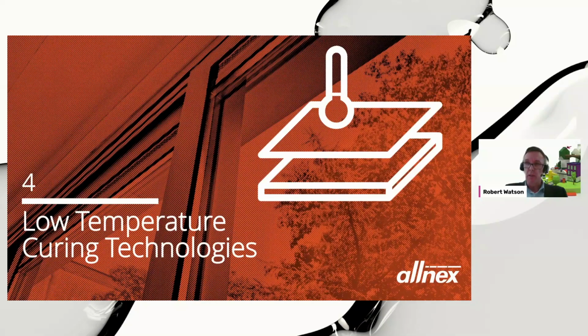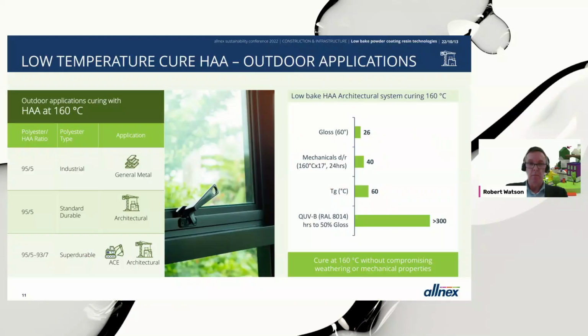So let's just delve into these low curing technologies a little bit further. And I've got some examples here. So this first one is an example of hydroxyalkyl amide. Again, very important for the European market. And we're showing here that it's possible to have HAA cure at 160 degrees centigrade, range of polyester cross-linker ratios, different types of polymer, whether it be a general industrial type polymer where there's no weathering specification, or standard durable, super durable, that architects put specifications on the coating to have certain weathering performance characteristics.